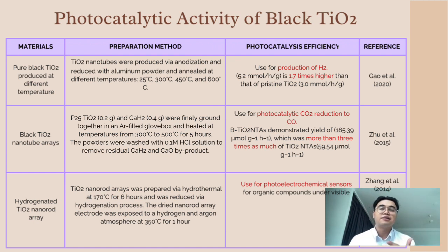Next is the CaH2 reduction method. The materials produced are black TiO2 nanotube arrays. It is used for photocatalytic CO2 reduction to CO. And the black TiO2 produced here demonstrated a yield of 185.39, which was more than 3 times as much as TiO2 nanotube arrays. And the third method is hydrogenation.